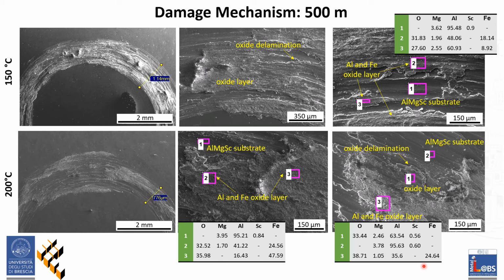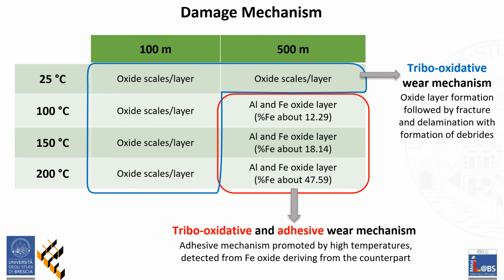Even after 500 meters, oxide forms and fractures, as can be better seen in the central and right images. Therefore, as summarized in this slide, triboxidative wear mechanism is observed after 100 meters for every temperature and also at room temperature after 500 meters. This damage mechanism involves the continuous oxide formation and fracture. For the 500 meters conditions, at high temperatures, also the adhesive wear mechanism takes place, as revealed from the iron presence.